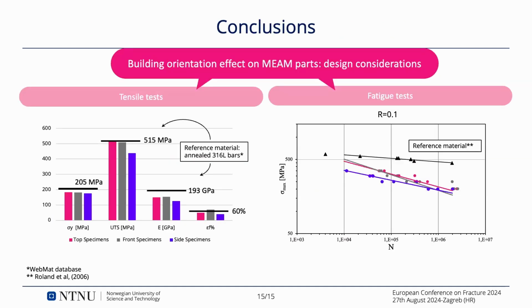To conclude, we can compare our material to a reference material. And speaking about tensile tests, the closest to these requirements, to these target values, are top and front specimens. While for the fatigue tests, it's more difficult to make a proper comparison, but still we can infer that 316L should give more in terms of fatigue resistance.